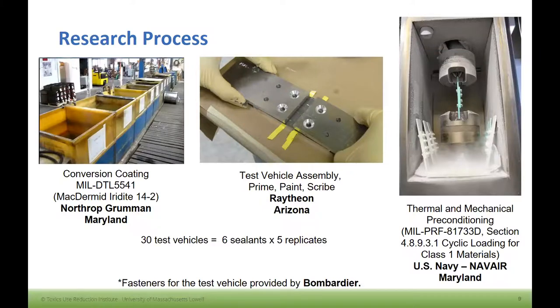So just to give you an idea of the actual process and how all the different participants were involved. To do this evaluation, we put the conversion coating on the panels at Northrop Grumman down in Maryland. Then the panels went to Raytheon in Arizona, and they did the priming, the painting, the scribing, and the assembling of the test vehicles. Then prior to the testing, we did some preconditioning at the US Navy in Maryland, both thermal and mechanical. We put them in a chamber and cycled the temperatures between hot and cold, and at the same time, we had the test vehicles under load throughout that thermal cycling, to really stress the joints and the sealant in between the joints.